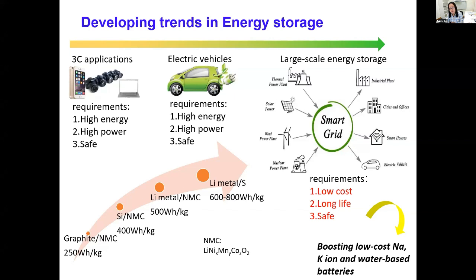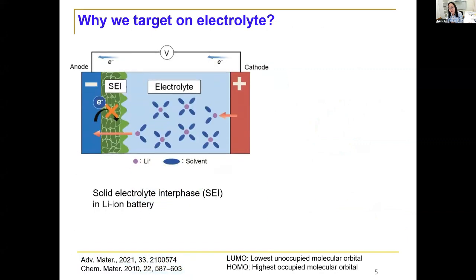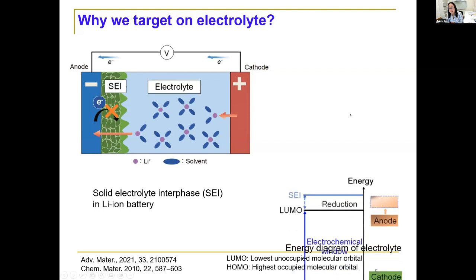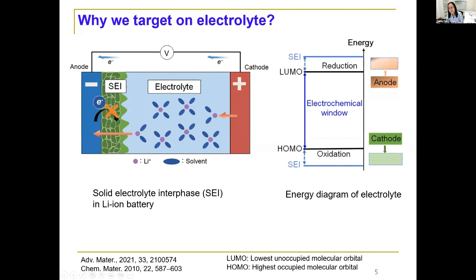Then you probably know the electrolyte is actually the reason for the instability of the lithium-ion battery, because the lithium battery uses an organic flammable electrolyte. And the electrolyte not only influences the safety, but also the electrochemical performance of the battery, because the battery reaction is just the electrode interface reaction. So the stable electrochemical working voltage window depends on the LUMO-HOMO value of the electrolyte, of the anode and cathode, and also the stability of the electrolyte.